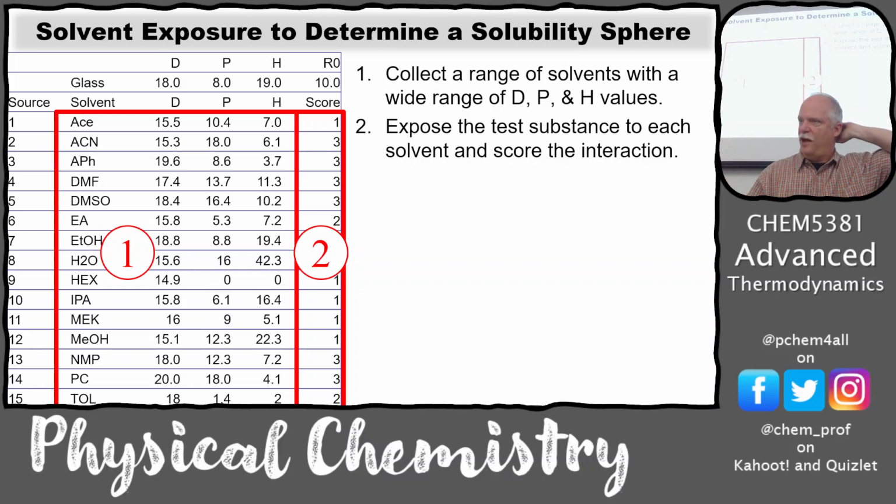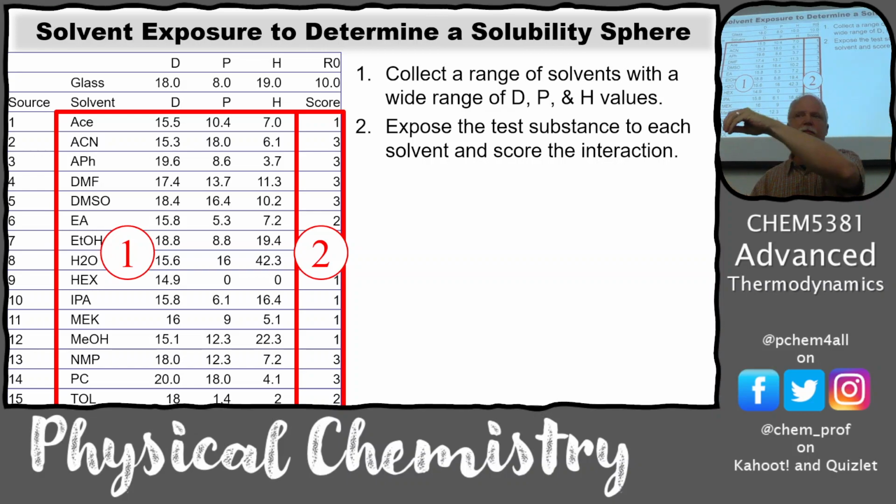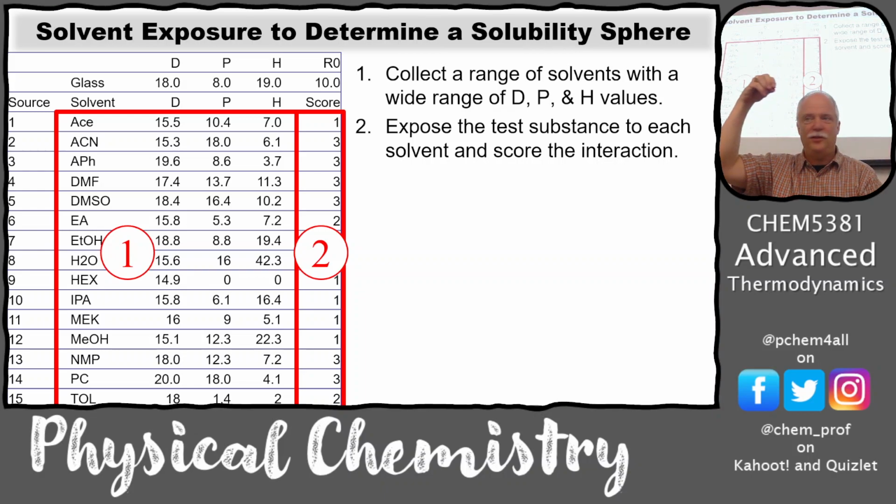And if you have a polymer or some kind of substance in your research that you want to find a good solvent for, or find the DPH values for, get 20 solvents, 20 vials, put a small amount of your substance in each vial. Then each solvent goes in there, and you can count the drops. You can do it by mass too, but you can put a drop of solvent in there and shake it and see if it's homogeneous. Some solvents will dissolve your 0.1 gram of substance with one drop. That's a good solvent, right? You shake it and you look, it's homogeneous, mark it down.